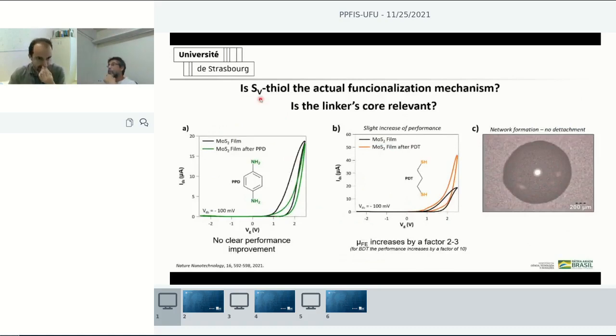Last but not least, we asked ourselves: is the sulfur vacancy healing the actual functionalization mechanism responsible for what we observed? And is the linker's core relevant? So we performed two experiments. Here we have two transistor curves. One where we functionalize the molybdenum sulfide film with this molecule that has an electron delocalized core but two amine groups, so they are not able to heal the sulfur vacancies. And what we observe is that the performance is nearly the same. No current increase. So this molecule cannot do the job of the BDT.